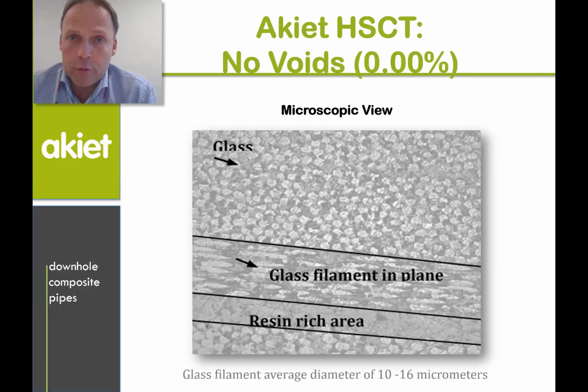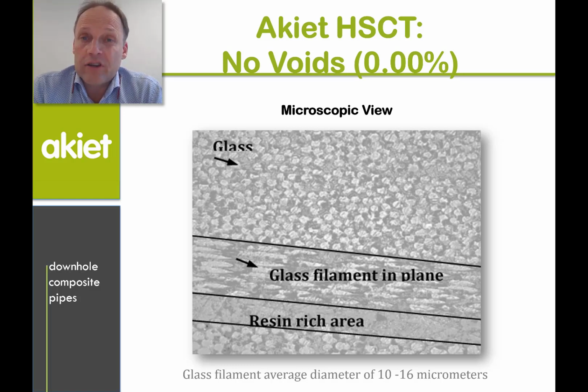Microscopic view of a cut through a composite body, which has alternating layers of glass that are perpendicular to the cut, and those that are almost parallel to the cut, which shows long ovals of the glass filament in plane. And there's a resin-rich area, which is only resin, there's no glass there. Just about the scale of this slide, a typical glass filament will be about 10 to 16 micrometers. So that's about 1/100th of a millimeter. If there were any voids in this cut through, they would show as black. And as you see, there are no black voids in this structure.